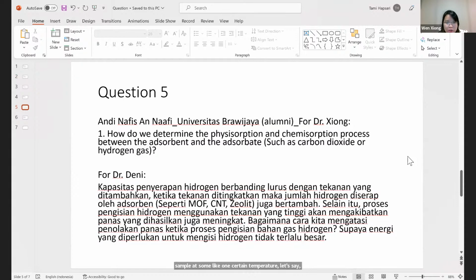Then you have the total amount of both physisorption and chemisorption, and then you do the evacuation for enough time, like 2 hours, 3 hours, whatever you need. During the evacuation, the reversible physisorption will desorb from the surface. Then you dose CO2 or hydrogen again to the surface. This second time, the amount of gas adsorbed on the surface is the physisorption amount.